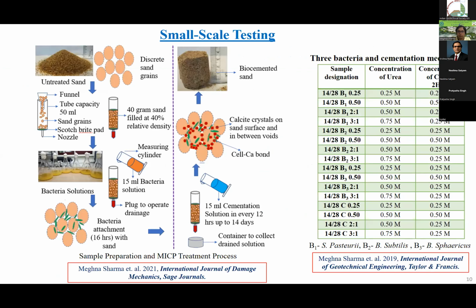Okay, so I conducted initially a small scale study to analyze what will be the effect of different concentrations of urea and calcium chloride dihydrate. What will be the effect if I treat it up to 14 days duration or 28 days duration, and with different types of bacteria. It was a simple procedure: I provided the bacterial solution to the sand and kept it for a few hours, and then the reagent solution was provided at every 12-hour interval, and then this calcite precipitation was achieved. Like this, the simple untreated sand got strengthened, and you can see the cylindrical specimen.